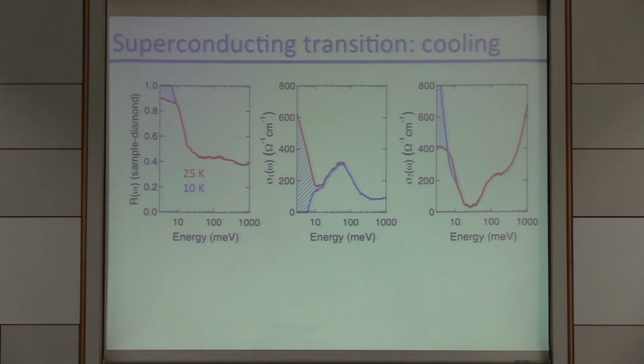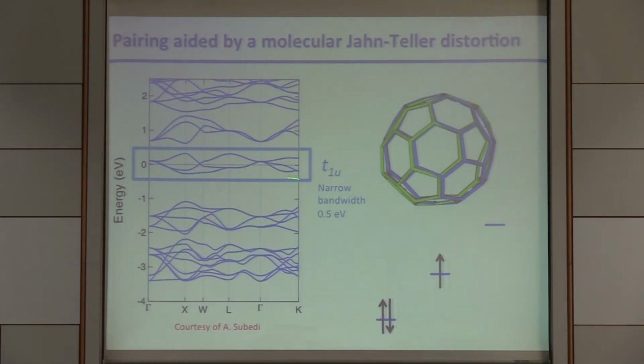The reason why this material becomes superconducting is that if I look at the lowest unoccupied molecular orbitals when I dope the buckyball 3 times, I have these 3 electrons, which without anything else would form a high spin state. But because of a Jahn-Teller instability, I have the formation of these singlet states, actually a linear combination of singlet states on each one of these 3 orbitals, and these are conducive to the formation of a superconductor.